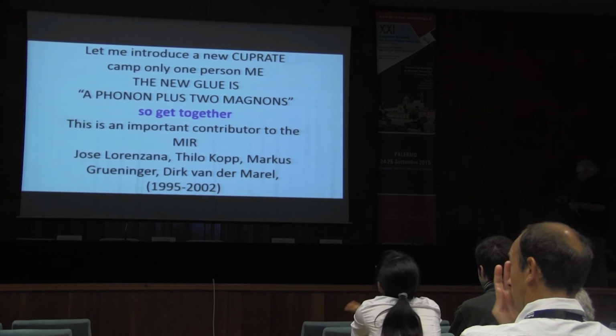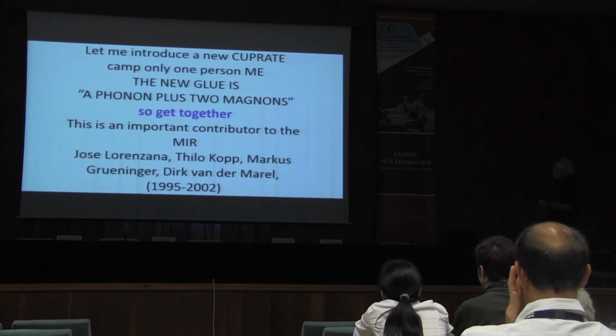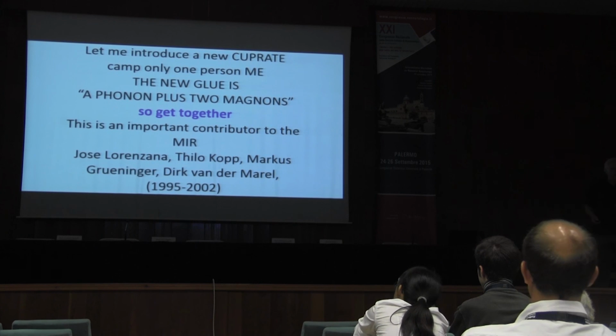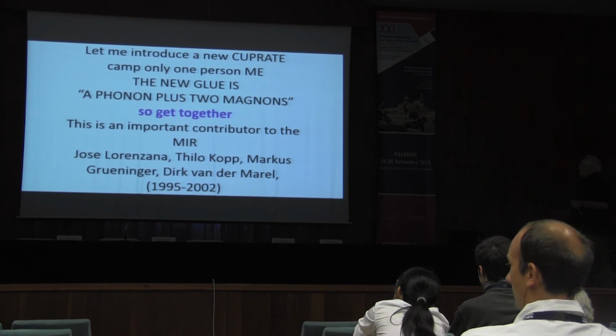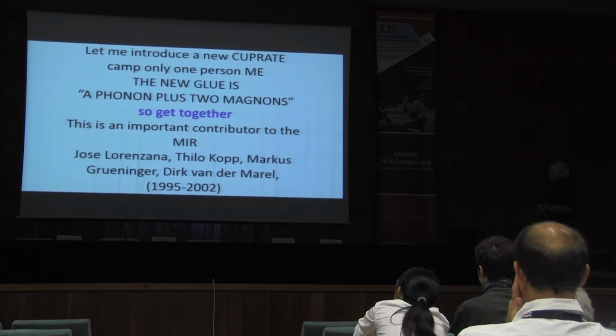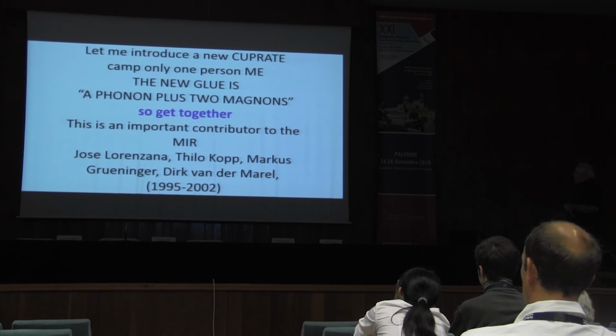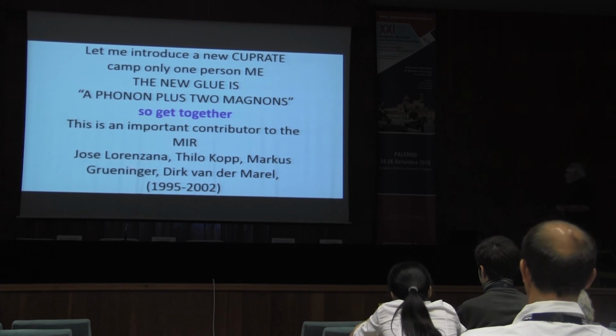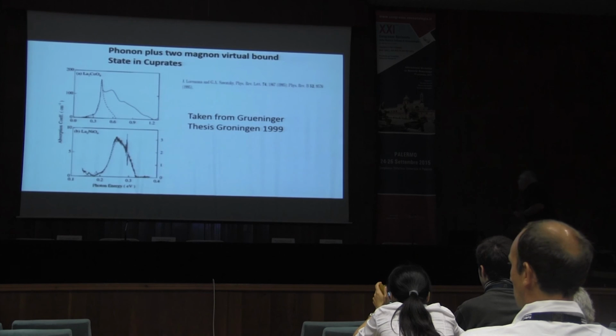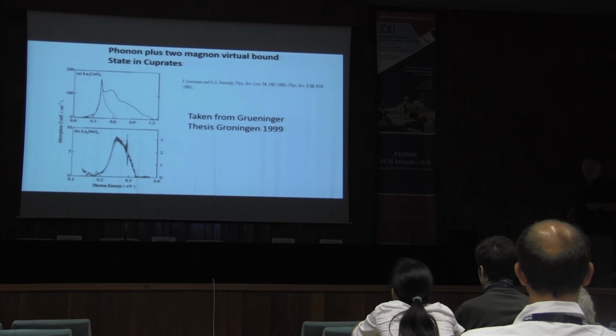Okay, so let me introduce to you a new cuprate camp, which has only one person in it, that's me. And the new glue is a phonon plus 2 magnons. Now the phonon and magnon people have to get together. Finally, they always have separate conferences, right? They should get together and form this phonon plus 2 magnons. This is an important contributor to the mid-infrared spectroscopy, as was shown by these people in these years between 95 and 2000 or so.